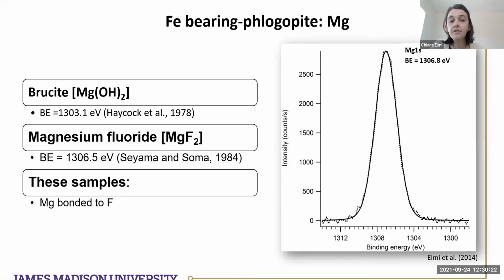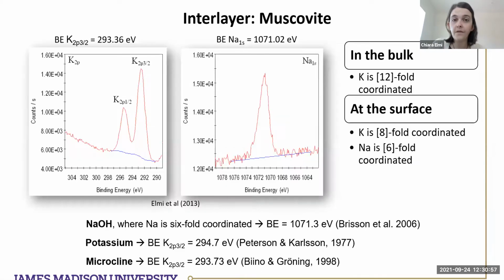The magnesium is a substitute of iron in the octahedral layer site, and you see that the binding energy is closer to the fluoride binding energy, magnesium fluoride. So the iron prefers the octahedra with the OH in the apex, and the magnesium prefers the fluorine. So there's more organization in the site than was thought before.